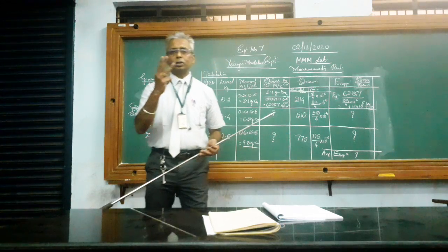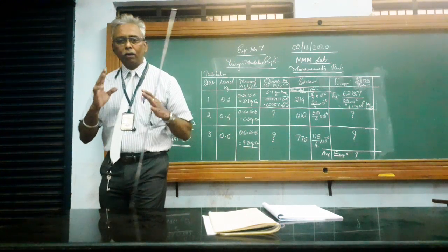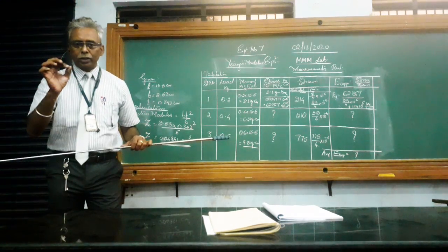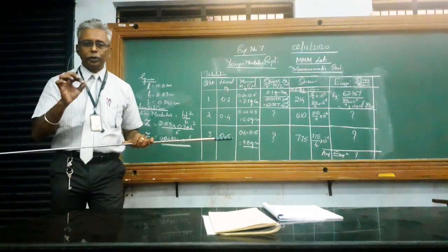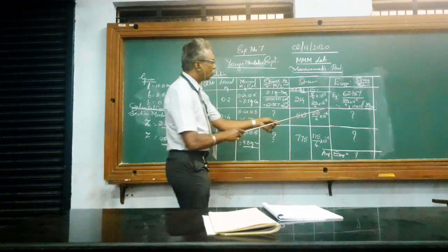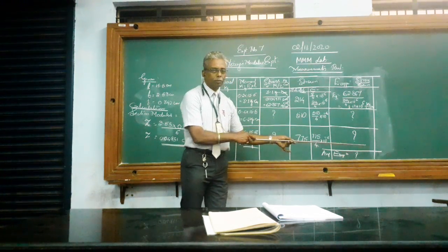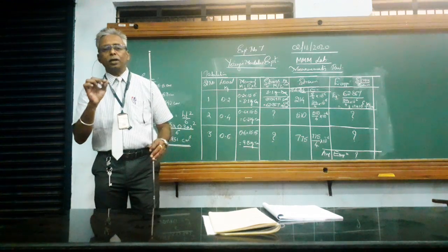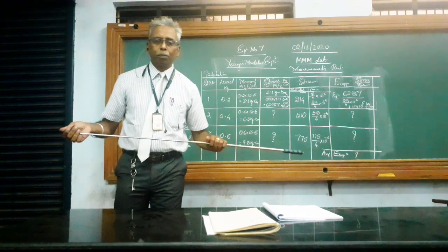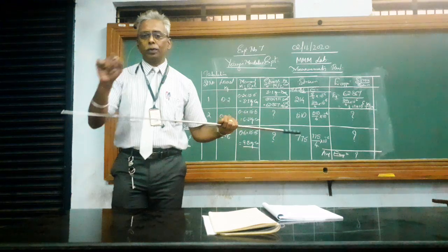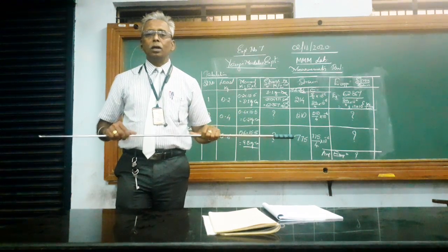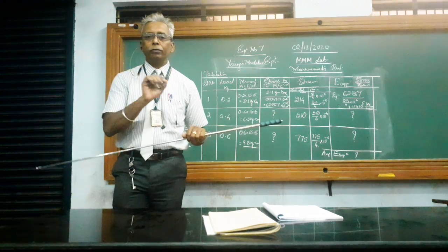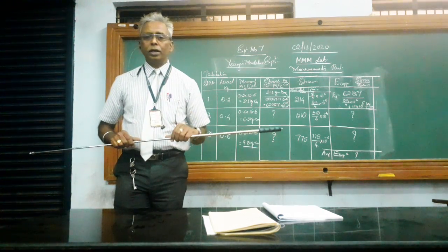Okay, one or two or three conclusions: we have conducted the experiment on Young's modulus of elasticity. The value of average Young's modulus was found out to be, let us say, 1.1 into 10 to the power 6 kg per centimeter square. Third conclusion is that the standard value of Young's modulus E for copper is around 1.1 into 10 to the power 6 kg per centimeter square. Our experimental value is favorably comparable with the theoretical or standard value.